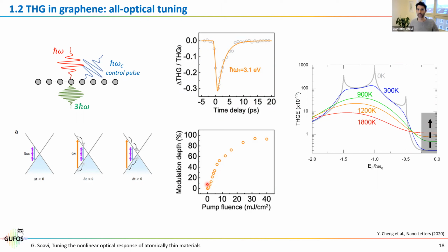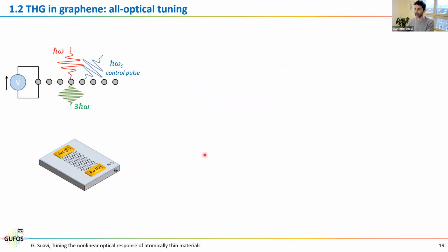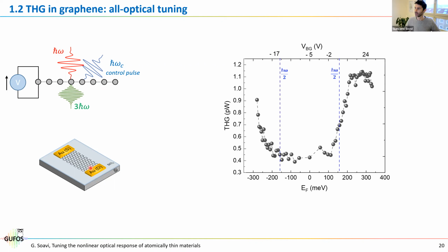And that's why we thought, okay, let's try to do the same experiment, but this time we combine optical excitation with electrical excitation. So now we can do all-optical modulation, but we can also combine it with different values of the Fermi energy and the gate voltage. So we have basically the same device as before, where we have a back-gated device. This time we use an encapsulated one. So we slightly change the experimental conditions, but the basic principle is the same. So first of all, we do characterization again. So you see this time we can reach both sides of the Dirac cone, so the p doping and the n doping.